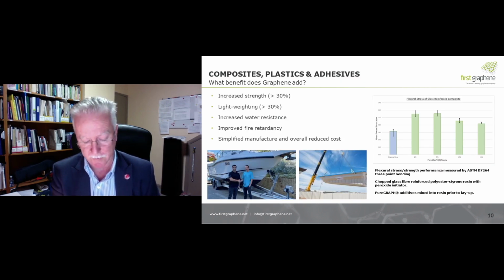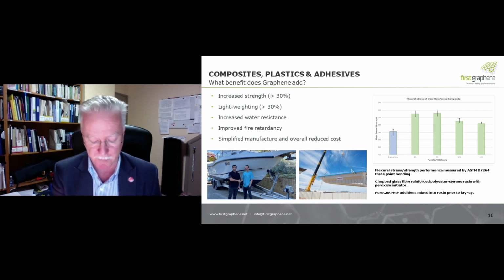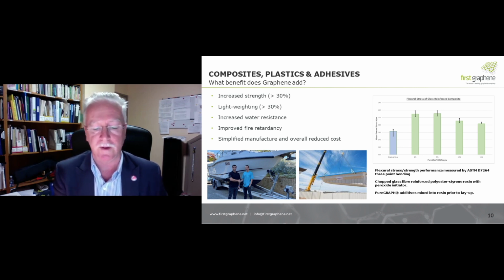To give you examples of what graphene can do when you add to the materials, consider the examples of composites and think of fiberglass here. We have successfully added 1% loadings of graphene to in-ground fiberglass swimming pools, achieving the following benefits. They can be made in 2 layers rather than 5, and in 80% of the time. And this gives the factory a 20% lifting capacity at no cost. The pools are 30% stronger and weigh 30% less.